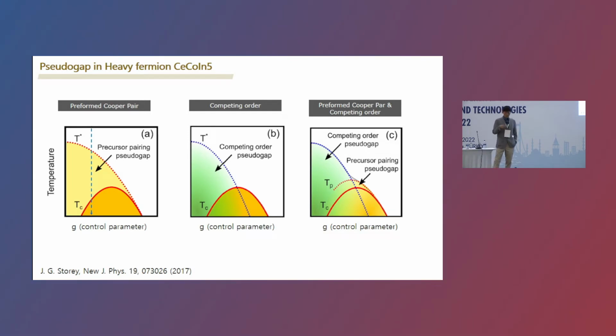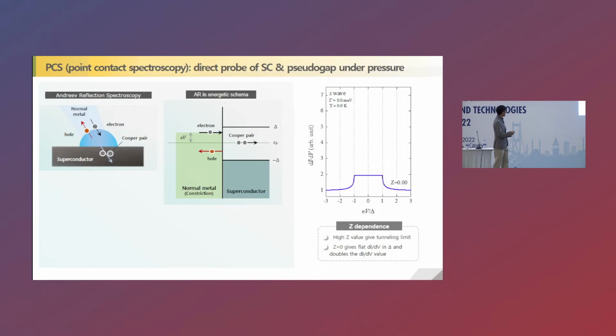So in order to probe the evolution of the pseudogap phase and the superconducting phase, we used so-called point contact spectroscopy, which can directly probe the superconducting gap and pseudogap under pressure. This technique takes advantage of so-called Andreev reflection spectroscopy, where one electron comes in and is reflected on the surface of the superconductor, making Cooper pairs in the superconductor, meaning that the differential conductance is doubled within this superconducting gap, in an ideal case where there is no contact barrier on the interface.